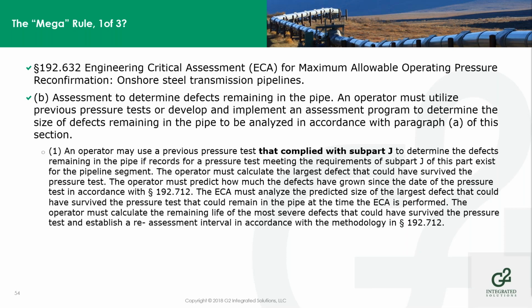For the ECA for this process, an operator must use a previous pressure test that complied with subpart J. You may use that pressure test if you have one, as long as it met the requirements of subpart J, and predict how much the defects have grown since that date in accordance with 712. You must analyze the predicted size of the largest defects that could have survived the pressure test that could remain in the pipe at the time.